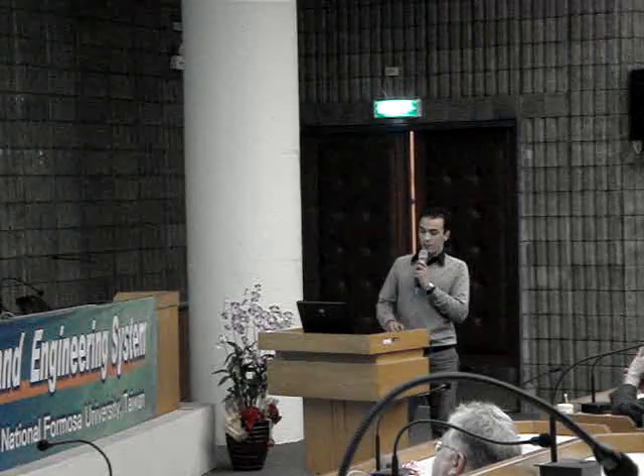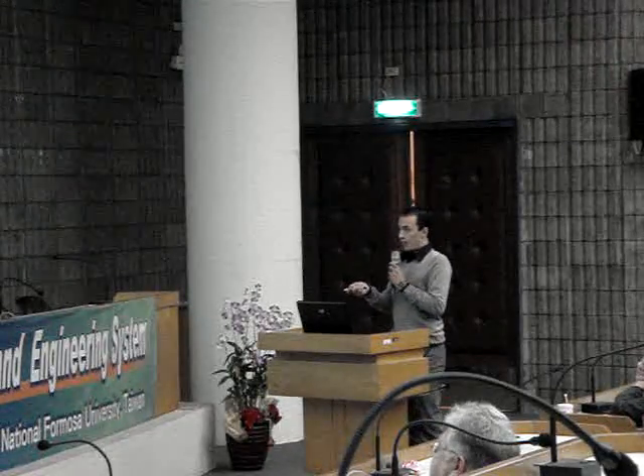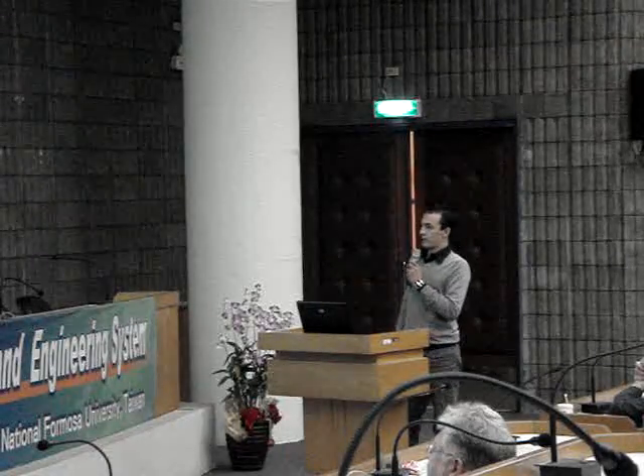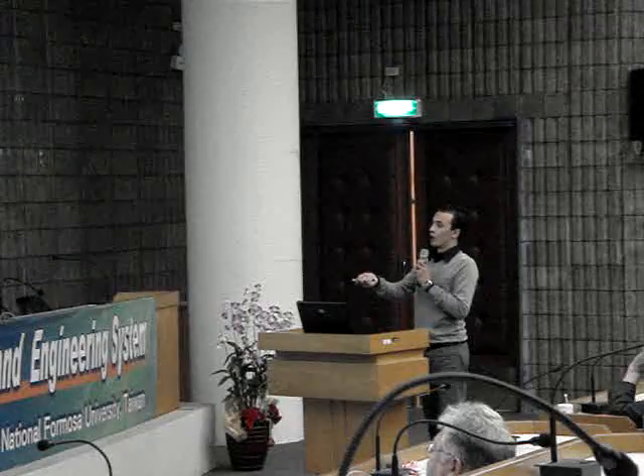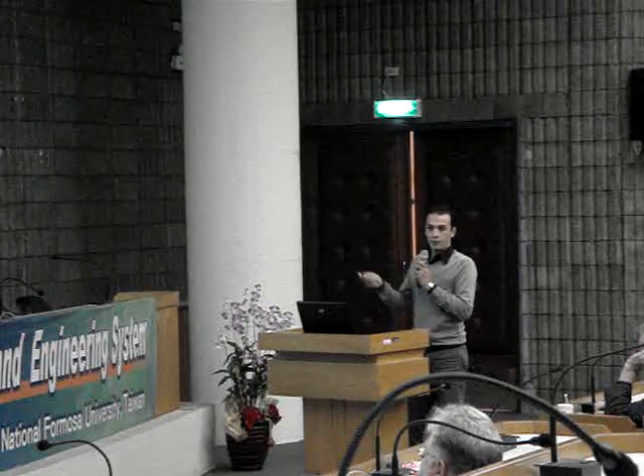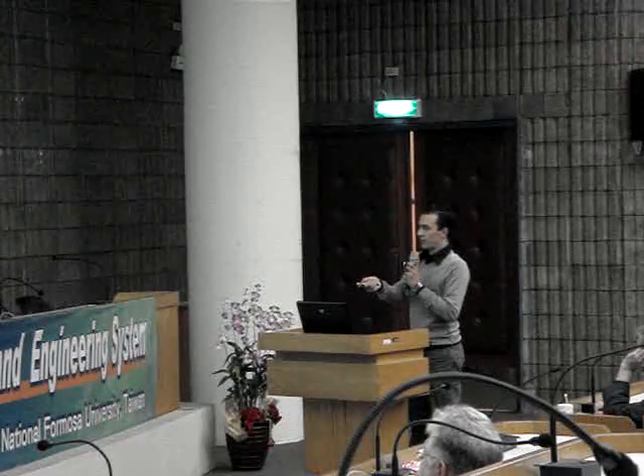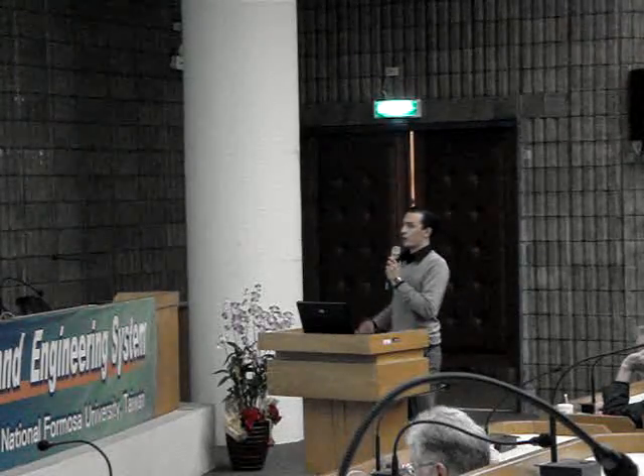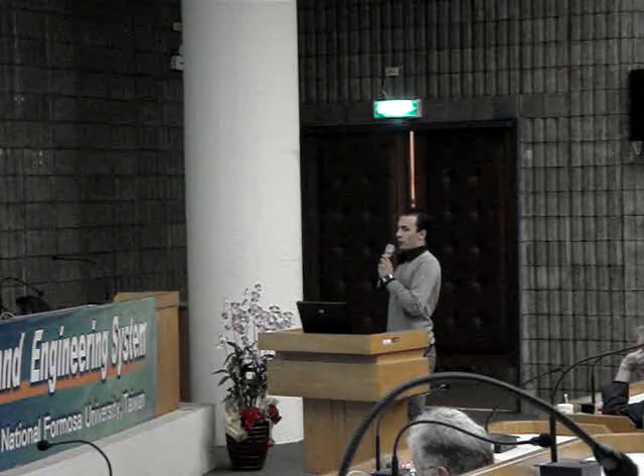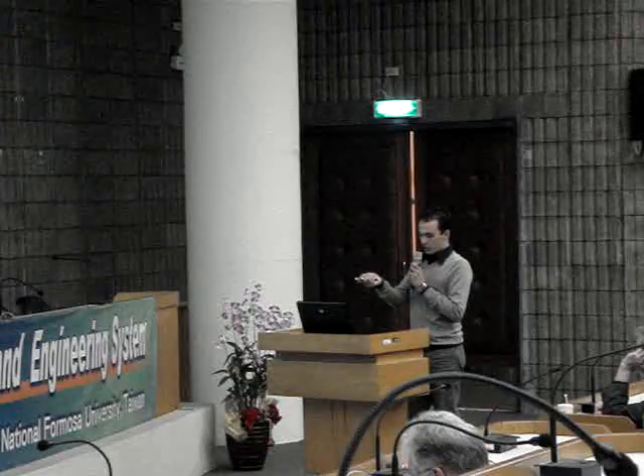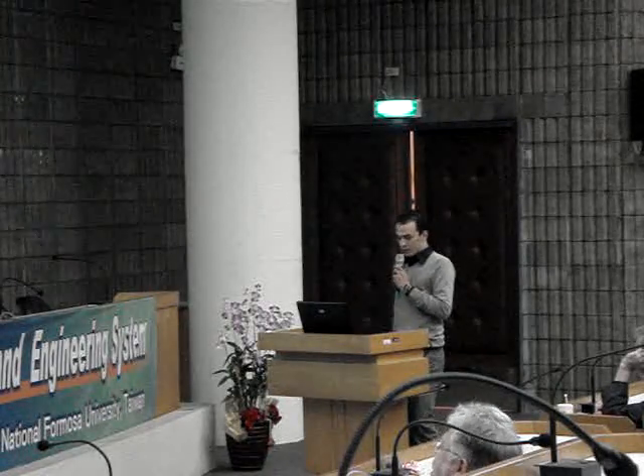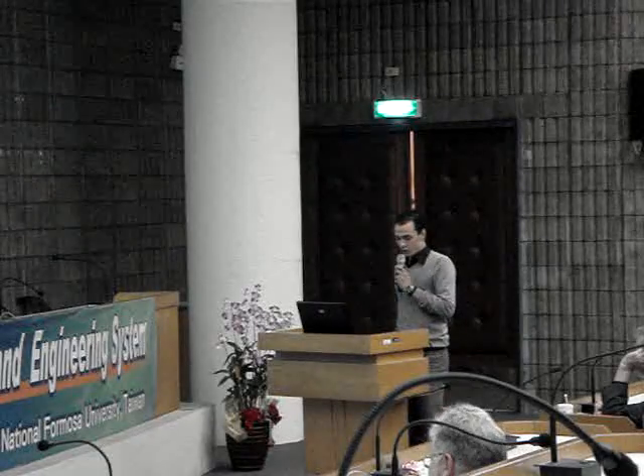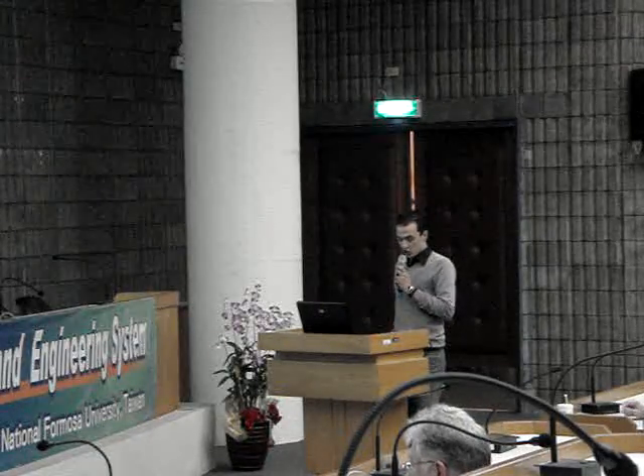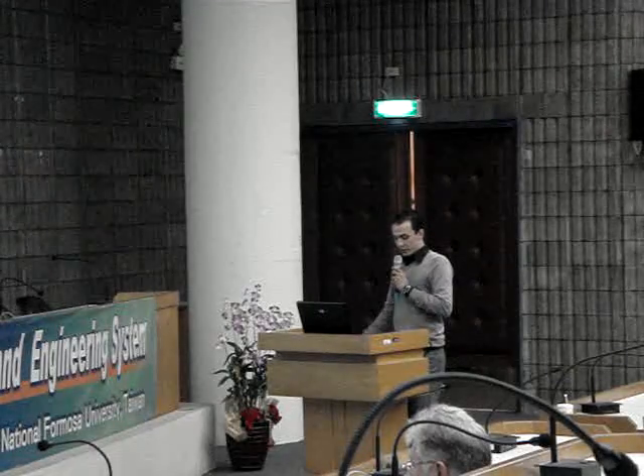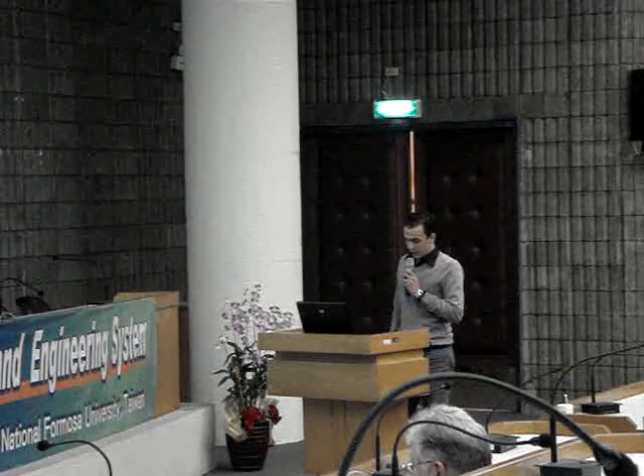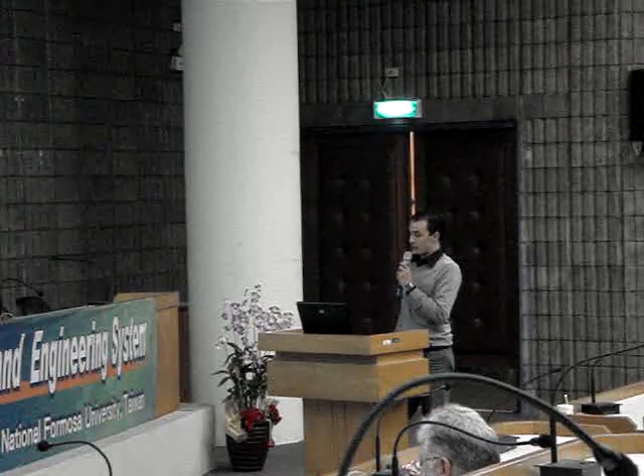And here, as an example for our process, is the golf club. Here is the 3D model that, as we said before, we make by rapid prototyping machine. And after that we make the 3D silicon rubber, and now here is the spray coating mold. As the picture shows us the result, the wax pattern manufactured by this high pressure spray technology has good precision and surface quality. Moreover, the pattern and the surface of the die can be duplicated exactly by this study.